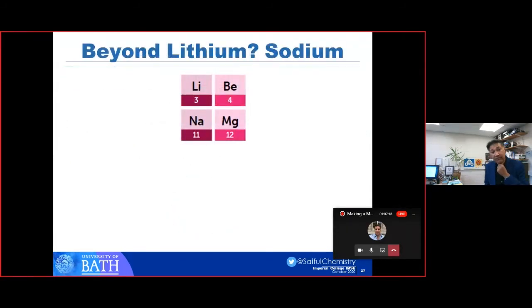The other new area is, can we go beyond lithium? And if you look at the periodic table, as a chemist, you could say rather than beyond lithium, you can go below lithium. And below lithium is sodium. Sodium has a similar chemistry to lithium. It just happens to have a higher mass and a larger size. And right next to sodium is magnesium, which actually has the same size as lithium, but double the charge. Beryllium isn't looked at because it's highly toxic. So really, beyond lithium, there's a big research effort on sodium.